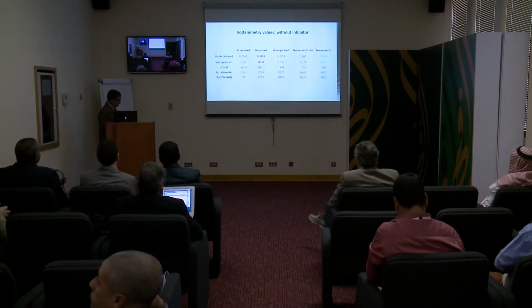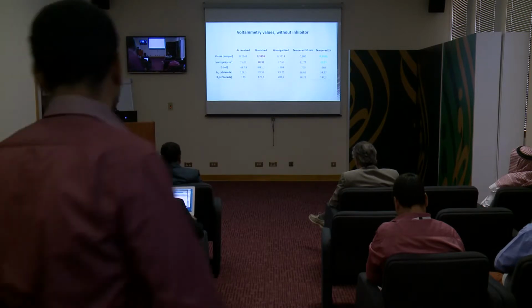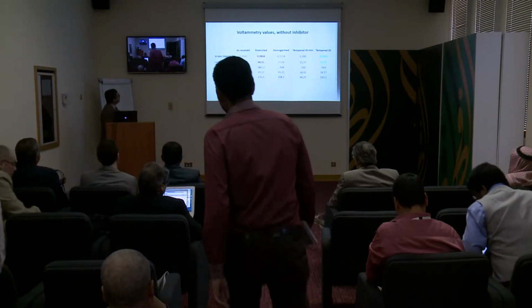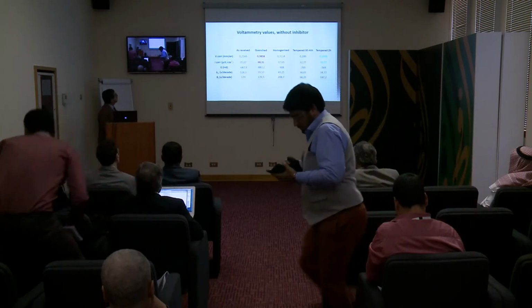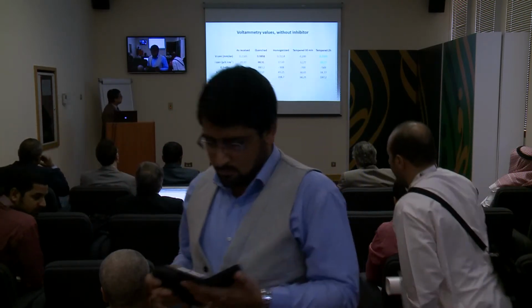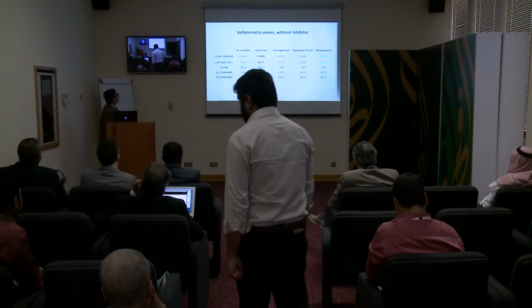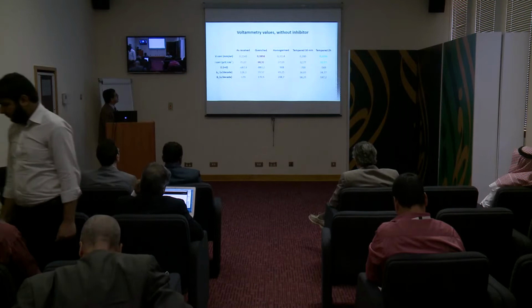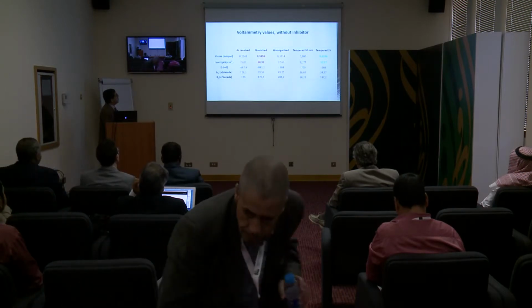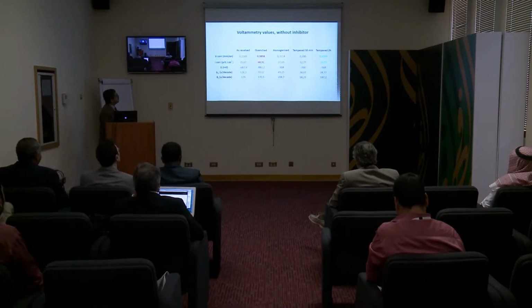Practically the results, I'm sorry, it's not very clear. I can indicate this data, which indicates the results of voltammetry. By comparison between the as received material and the quenched one, we have a worse behavior for the quenched one, and we have a better behavior when we make tempering of martensite.